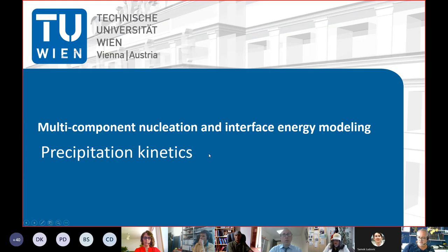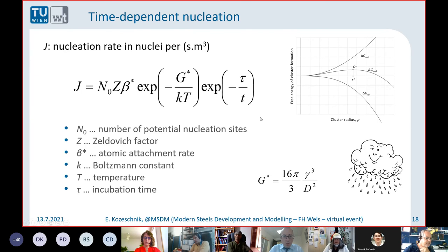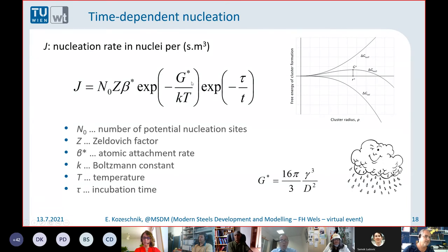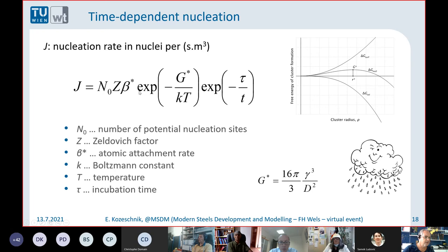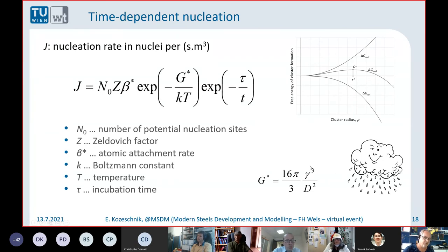Once the growth and shrinkage problem is solved, there's still the part where we have to discuss nucleation. Just a short summary of the essence of what we use in MatCalc: we use the very classical formulation of the nucleation rate, where the nucleation rate is proportional to an exponential term. We have G*, which is the height of the nucleation barrier. Here's a sketch of a typical nucleation barrier, and you can see G* as the maximum of that barrier. These coefficients here are more or less determined — I'll show that on the next slide. Just keep in mind the G*: it is the height of the nucleation barrier, and in classical theory this is related to the interface energy cubed divided by the driving force squared.